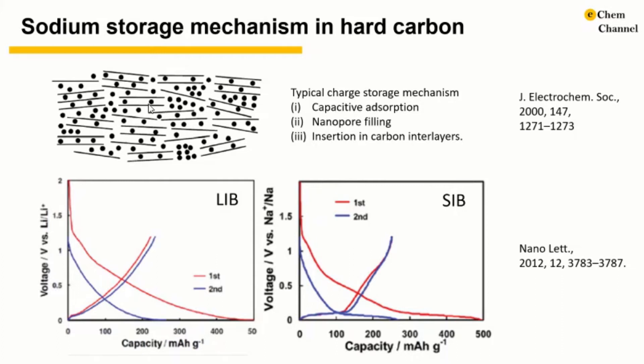Hard carbon is an amorphous carbon material without an exact crystal structure model, making it difficult to investigate the physical and chemical changes during the sodiation and desodiation process. For these reasons, different sodium storage models have been proposed in recent years. The models can be summarized into three categories: capacitive adsorption, nanopore filling, and insertion in carbon interlayers.